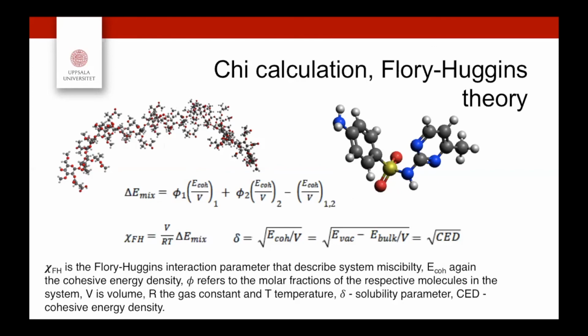So if it goes higher than 0.5, I think the system will definitely phase separate. If it goes lower than 0, then it will quite likely be well mixed. So these are the values that could be measured relatively easily, but again, that would require a lot of small, relatively short simulations. But this is something we do.